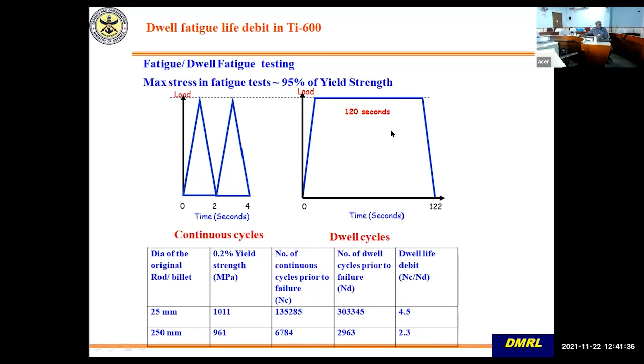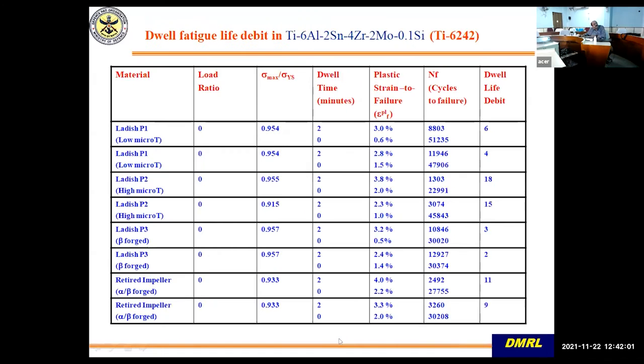Now this happens at lower temperature, that is below 200 degrees centigrade. Now, if you see this, in this, the dwell debit is lower. But along with that, what you see is the fatigue life, both continuous as well as dwell cycle, is much lower. Okay, so you can see the effect of processing and microtexture on fatigue life.